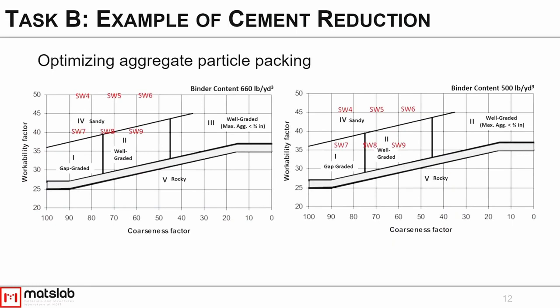We then used coarseness factor charts to determine what the workability of the systems would be with these aggregates. And we were able to choose the right blend of aggregates to increase our total packing without significantly reducing workability. So we saw maybe 5 to 6% increase in total volume of aggregates over standard mixtures that were already being used, which is quite a bit in terms of reducing cement content.